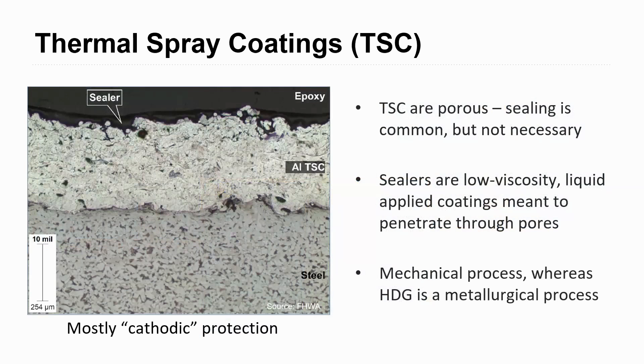You have the option to use a sealer or not — sealers are probably more common than not. The thermal spray coating is typically porous, so sealing can be used to address that, although there's some discussion that it may not always be absolutely necessary. That's a function of the coating thickness: the thicker you go, the less permeable it gets, and there becomes a point where permeability goes to zero and you don't really need a sealer. This is a mechanical bonding process, requiring that angular profile for the alloy to bond to the steel surface.